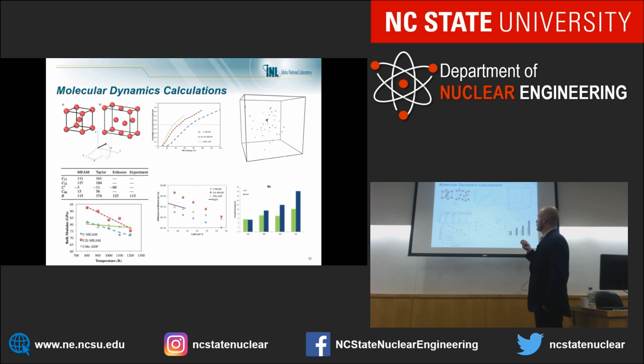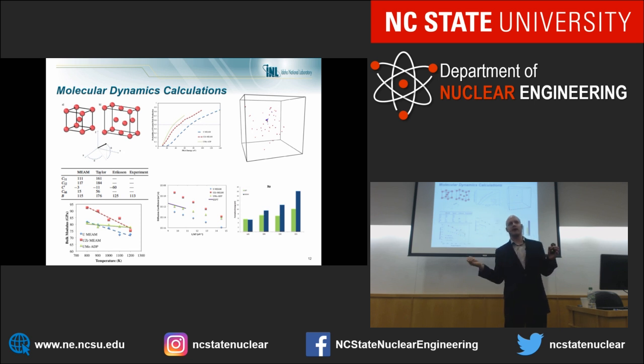And we're seeing the results vary by a factor of 2. So threshold displacement energies from 30 to 60. This is a huge change. And that's, if we take these numbers, we usually calculate displacements per atom in reactor or in irradiation experiments through a displacement energy put into the NRT equations to approximate the amount of damage.